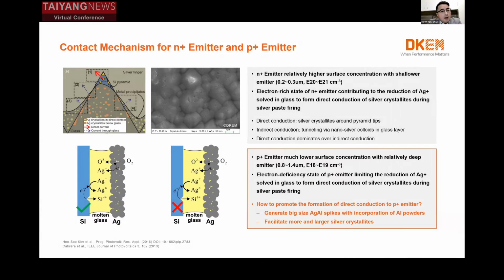From this page, firstly, I would like to talk about how to achieve a good contact with p-type emitter for TOPCon solar cells. It's quite different from the n-type emitter like the PERC. Compared to the n-type emitter, the p-type emitter's surface concentration is much lower, and the junction depth is much deeper. Generally, the depth is around 0.8 micron to 1.4 micron, and the concentration is mainly around E18 to E19.